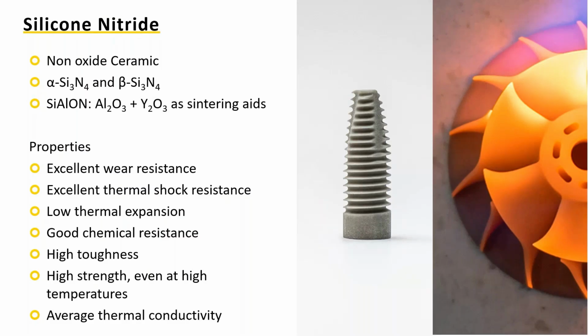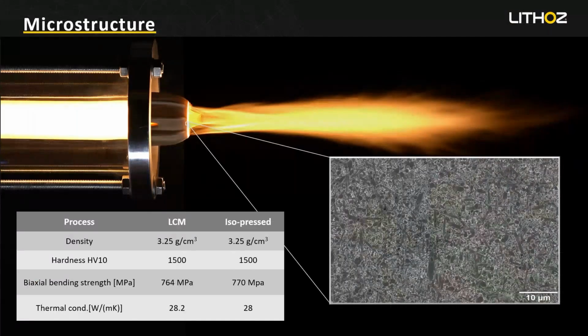I chose silicon nitride to show off how we compare ourselves. If we develop a material, we aim to achieve the same properties as the powder supplier would get with traditional forming. And here we have, for example, the density, the hardness, the bending strength, and the thermal conductivity reached and shown that we are on par with traditional manufacturing. On the right hand side, you see the microstructure of silicon nitride. As you can see, there are no defects or anything.